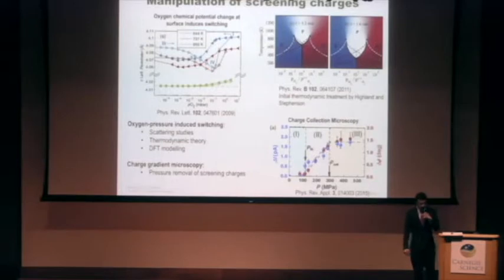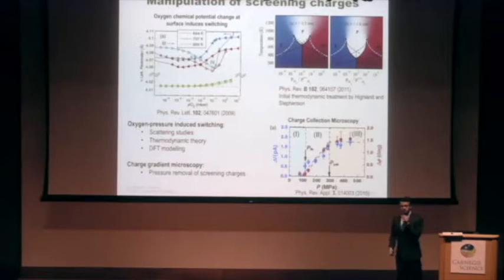One of the really good works in the last decade in ferroelectrics has to be coming out of Argonne, in this particular work by Highland and Stephenson. What they did was they took an ultra-thin ferroelectric film, lead titanate, I think it was less than 5 nanometers or so. They put it into a chamber and changed the partial pressure of oxygen at slightly higher temperatures. And what you clearly see is that by simply changing the partial pressure of oxygen, they're able to induce ferroelectric switching.